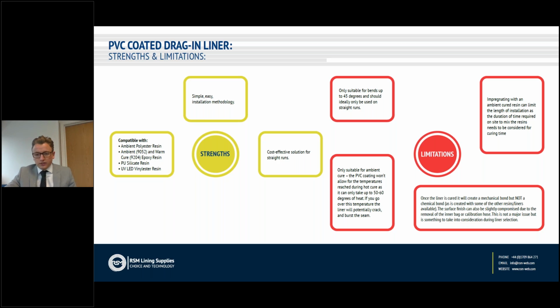Once the liner is cured, it will create a mechanical bond with the pipe that it's within. However, it won't create a chemical bond. What we mean by this is that when it cures, the resin stays inside of the felt as opposed to transferring onto the outside. So therefore you aren't getting any chemical attachment to the pipe that is already there. This is not a major issue, but it's something to take into consideration during your liner selection.